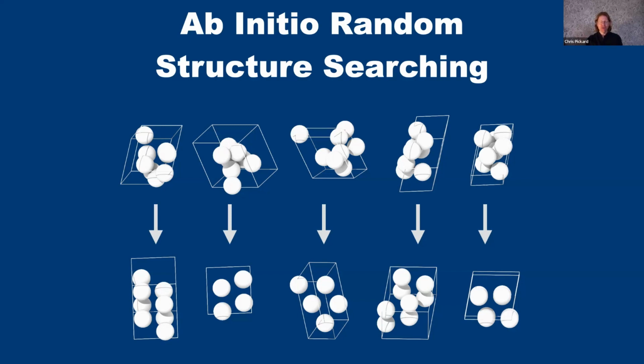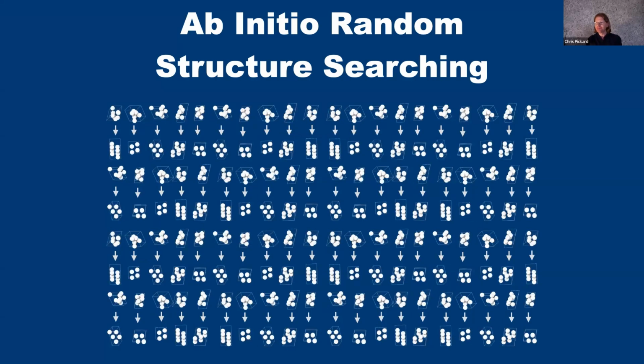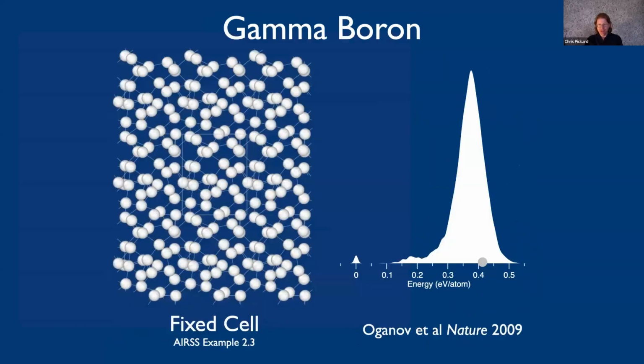But at the time, this was a revelation, and it meant we could do the calculations multiple times in parallel. If you could randomly sample the configurations, geometry optimize them and locate multiple local minima, and do it enough times, then you start to saturate the energy landscape and pick out the large basins in that energy landscape. And hopefully, if you do it enough times, you will map out not just the ground state, but all the likely metastable states as well. Now, of course, there's the question of what's enough times, and I'll come back to that in a little while.